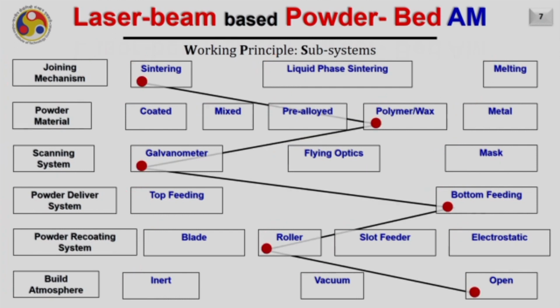So, let us now start discussing different combinations of the subsystems available in laser beam based powder bed additive manufacturing. Let us consider first, if the joining mechanism is sintering, it uses polymer as the powder material. It uses a galvanometer to scan the laser beam onto the powder bed. It feeds the powder from the bottom, and rollers are usually available to spread the layer onto the powder bed. Also, it happens in an open environment. This used to be the first system by EOS where polymer was used, and this type of arrangement was preferred. I may be missing some of the previous systems, but this was the most popular one.